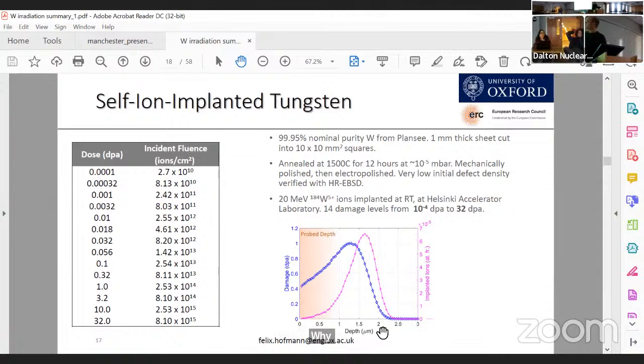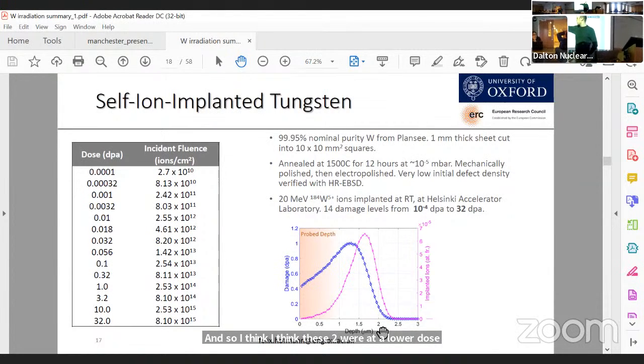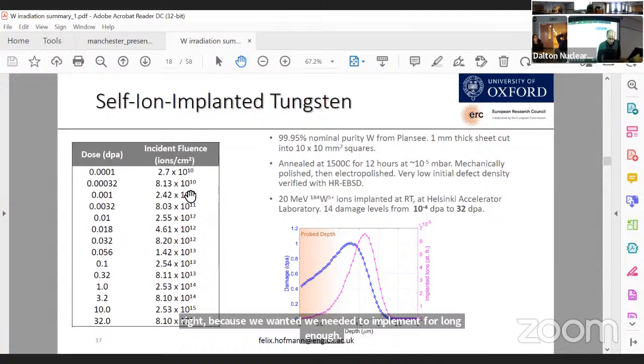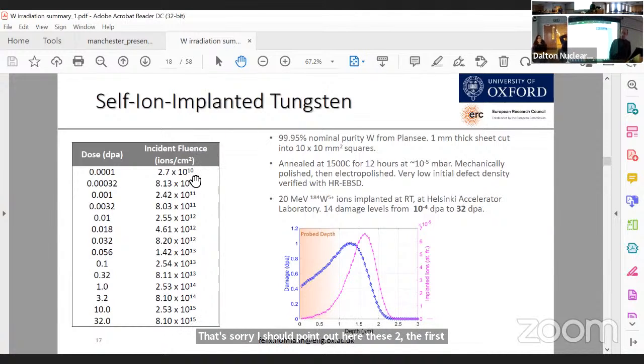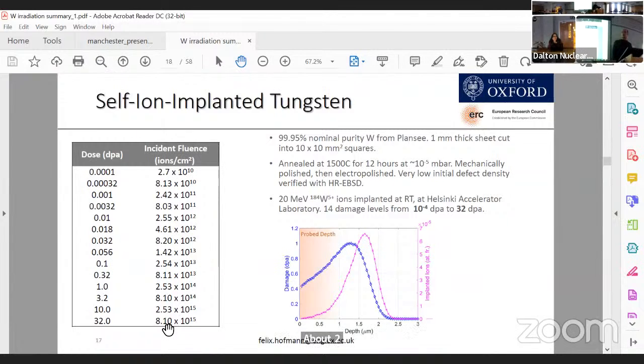Now hang on, there's a question of dose rate, right? I think these first two were at a lower dose rate, because we needed to implant for long enough to have a vaguely uniform coverage. Then these were all, I think, at the same dose rate, up to 1 dpa, and then the last three were at a higher dose rate so that we could fit it within about 2 days. We did manage to convince ourselves that that spread of dose rate was small enough that it shouldn't have much of an effect, hopefully.